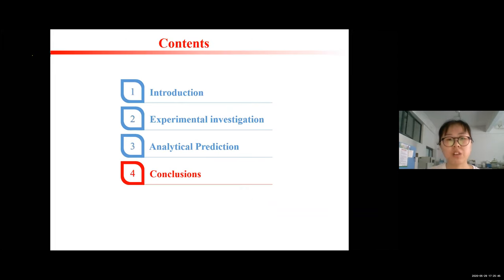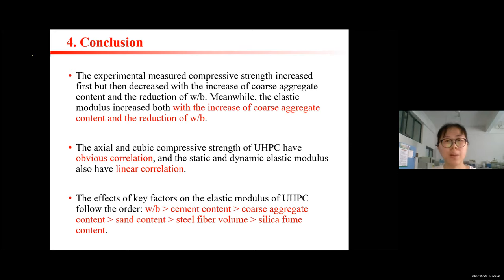And the last part is conclusions. Conclusions about the experimental result and the prediction result. We can see the elastic modulus increased both with the increase of aggregate content and the reduction of water to binder ratio. And about compressive strength, we have an obvious correlation. And the static and dynamic elastic modulus also have a linear correlation. About the prediction model result, we can get an order about the factors influencing the elastic modulus with the